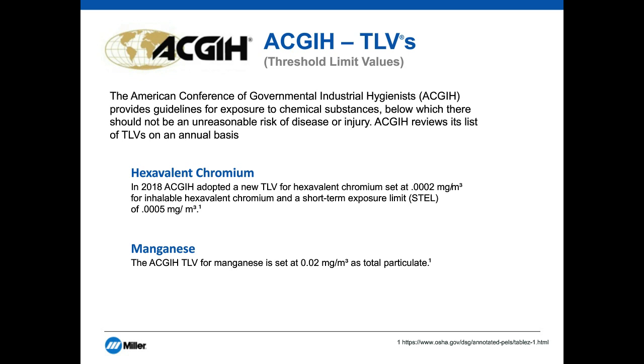You'll see the two compounds I just talked about, hexavalent chromium, which is given off from stainless steel base metal. They've established a relatively low exposure limit, as you can see on the chart, well below the OSHA permissible exposure limit. Likewise, manganese has a much lower exposure limit, 0.02 milligrams per cubic meter. This is some 250 times lower than the OSHA PEL. It's always considered good practice to try and reduce exposures not only below the OSHA limits, but below the threshold limit values, which again are the most current thinking.